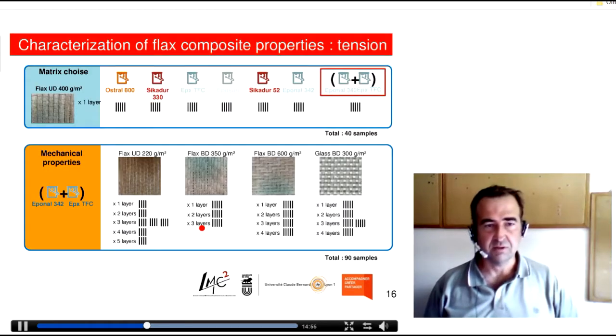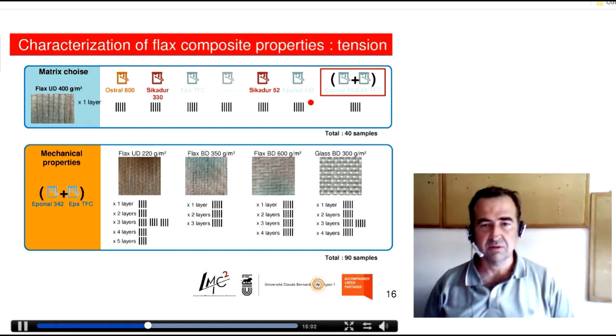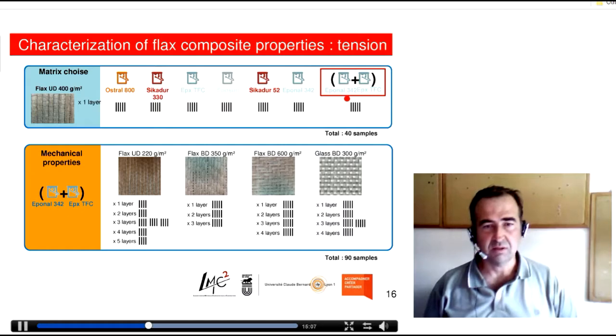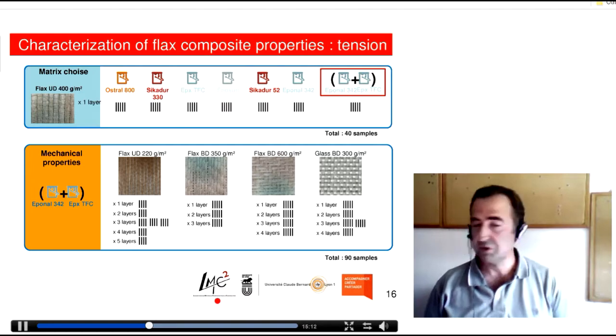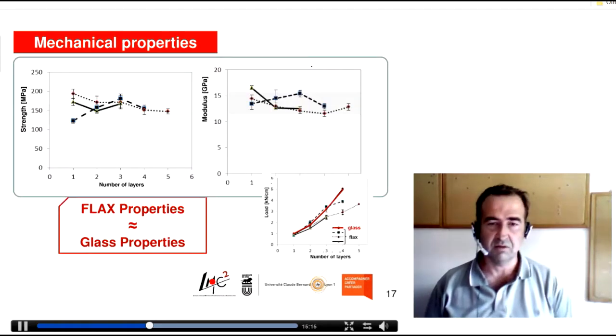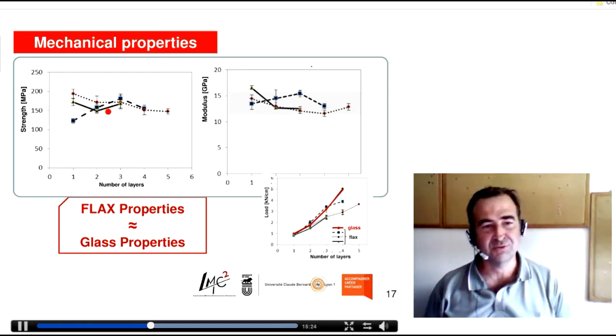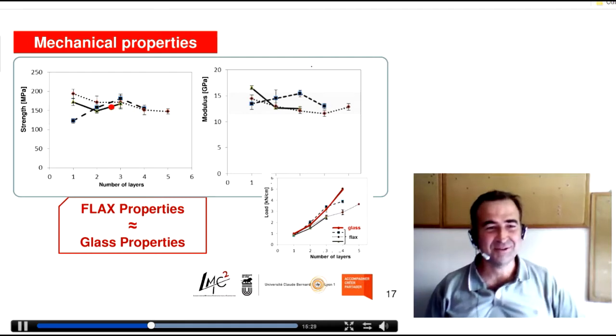So here you have several epoxy systems that we have tested in order to get different layers and optimize the best one. And this was at the end the best system from which we get the higher mechanical properties. So this is mainly the different tensile strength. One first objective was to, depending on the number of layers, compare the different strengths we may have.